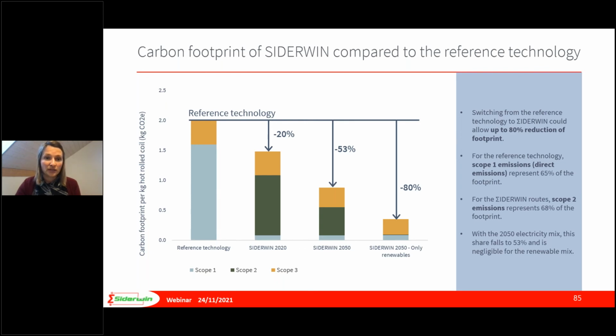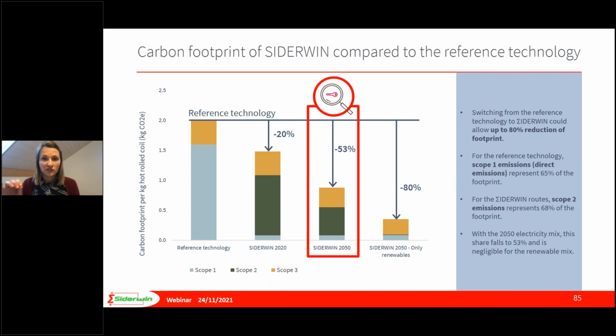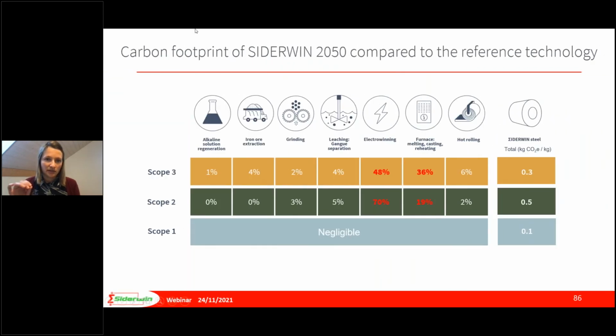And I wanted to show you then in more detail which stage of the process contributes to the Siderwin carbon footprint with the example of the Siderwin 2050 scenario. And this is what we can see here. So we can see the contribution of the different steps of the Siderwin steel production to the scope 3 and scope 2 carbon footprint. Scope 1 has a low contribution, and this is why we did not investigate it further in this graph. So we can see here very clearly that the electrowinning and furnace stages are the key contributors to both scope 3 and scope 2, and that they are the key hotspots of the carbon footprint.